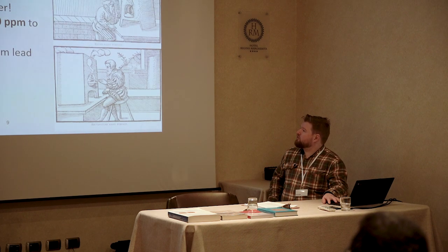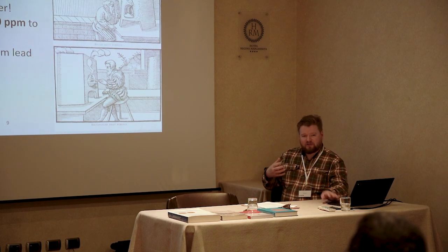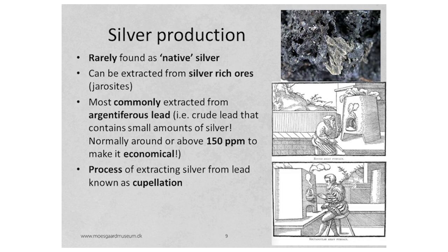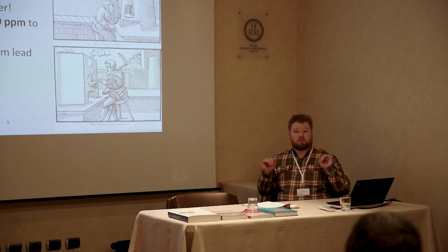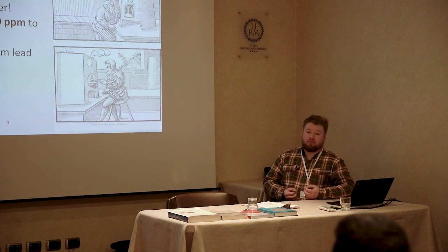And that's where you want to try and take the silver out. And when you do this process on a very large scale in the Roman period, also down to the very minute scale for those who are testing ores, alchemists, whatever, they want to see roughly how much silver is in. Essentially, you melt the lead in an alkali-rich environment, something rich in calcium, you know, with maybe a lime-rich clay with lots of shell, or you might have crushed bone ash, and the lead reacts with that to form lead oxide.